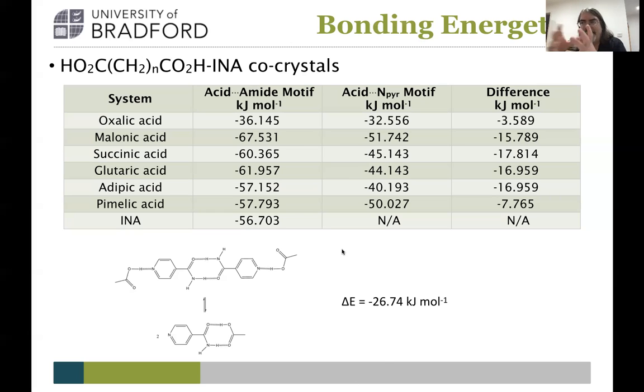So what these calculations seem to suggest is that when possible, we're going to go for the strongest ones. But if we can make three or four medium strength bonds rather than just one or two strong bonds, we're going to always favor the more collective system that builds overall stronger energy. And so that adds a complication into predictive studies, because we don't want to then just optimize and find the lowest energy interaction. What we really need to find is the whole set of possible interactions and look at how they can all pair up and combine with each other.